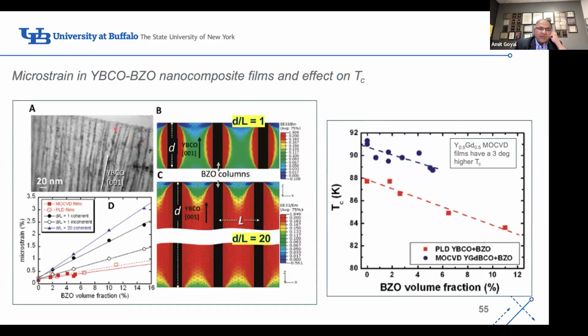It turns out that around each of these nanocolumns, there is still some residual strain, and that residual strain prevents incomplete oxygenation, which results in point defects. So as we increase the amount of these nanocolumns, the transition temperature decreases because we can no longer fully oxygenate the material. The red here is the strain, microstrain modeled by finite elements that we have done.